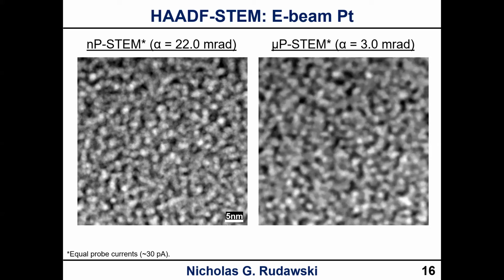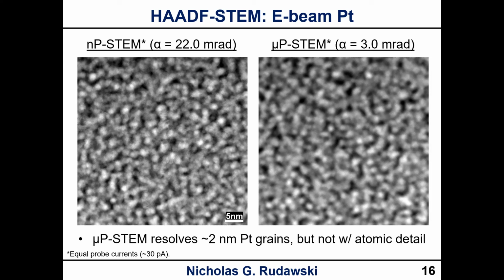If we look at the case for microprobe STEM, this is the same current, but we've cut the alpha value down to 3 mrad. So we're no longer seeing atomic detail, but we can still clearly resolve the grains, as we would expect.